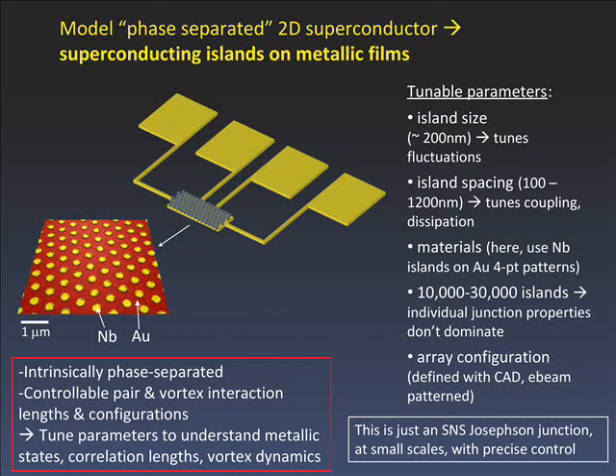This is the sort of system that we made — a model phase-separated 2D superconducting system. This is an AFM image of actual superconducting niobium islands, false-colored, on a gold substrate. We pattern these islands on a four-point patterned gold substrate: put current on the outer ends, measure voltage in the middle, and see what phase transitions occur as we change island properties. Each island is laid down using electron beam lithography, giving us complete control over island size, spacing, coupling, and dissipation. We've done experiments with niobium on gold, tin on graphene, and aluminum on topological insulators.